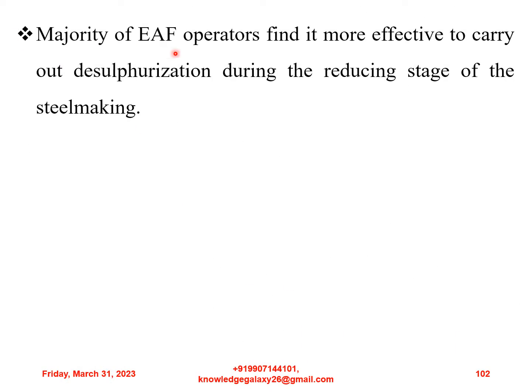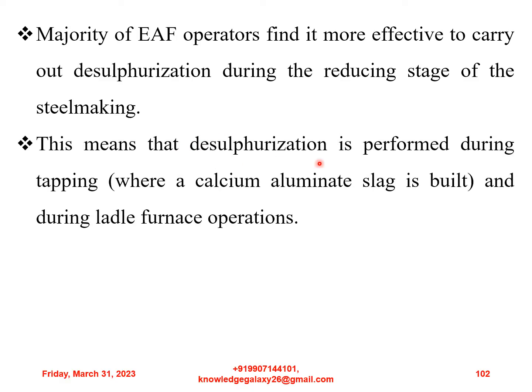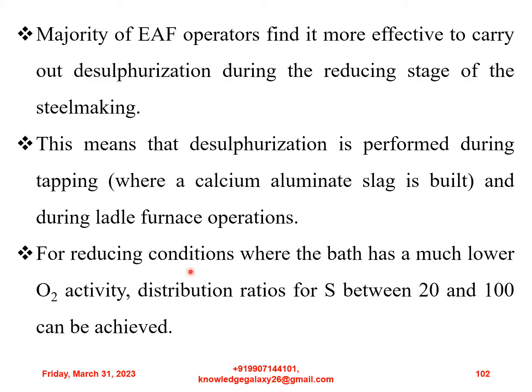The majority of electric arc furnace operators find it more effective to carry out desulfurization during the reducing stage of steelmaking. This means that desulfurization is performed during tapping, where a calcium aluminate slag is built, and during ladle furnace operations. For reducing conditions where the bath has a much lower oxygen activity, distribution ratios for sulfur between 20 and 100 can be achieved.